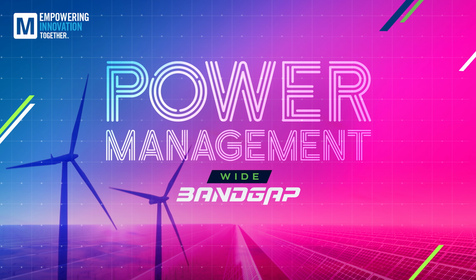Yeah, so wide bandgap refers to the energy bandgap between the valence and conduction bands of a semiconductor. Really, it's the amount of energy needed to knock an electron loose from the outer shell so it can move freely inside of the material. The main difference between a wide bandgap device like silicon carbide and GaN is that this energy is around 3.3, 3.4 electron volts, whereas in silicon, it's around 1.1 electron volts. So that's 3x the value of silicon for silicon carbide and GaN.